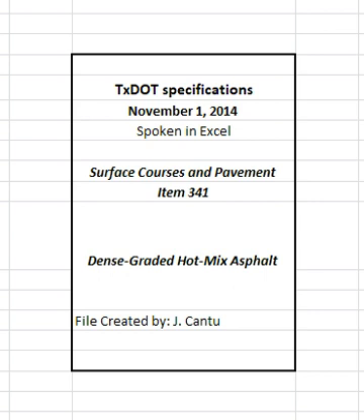The engineer may change the lot size before the contractor begins any lot. If the optimum asphalt binder content for JMF2 is more than 0.5% lower than the optimum asphalt binder content for JMF1, the engineer may perform or require the contractor to perform Tex-531-C on lot 1 to confirm the indirect tensile strength does not exceed 200 psi. Take corrective action to bring the mixture within specification compliance if the indirect tensile strength exceeds 200 psi unless otherwise directed.